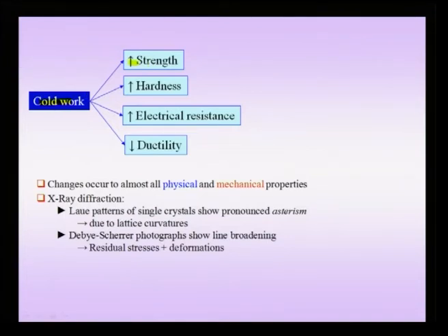So, cold work leads to an increased strength and an increased hardness. It also leads to an increased electrical resistance because of the point defect density increase and dislocation density increase, but the ductility of the material comes down. And changes typically occur to all physical and mechanical properties, which we call structure dependent properties or microstructure dependent properties. In X-ray diffraction, you will notice that Laue patterns of single crystals show pronounced asterism. That means they look star-like and are no longer well defined spots, and these are due to lattice curvatures. Debye-Scherrer photographs show line broadening, and in fact this line broadening can be used to characterize the strain in the material. That means we can compute the strain in the material by knowing the amount of line broadening.